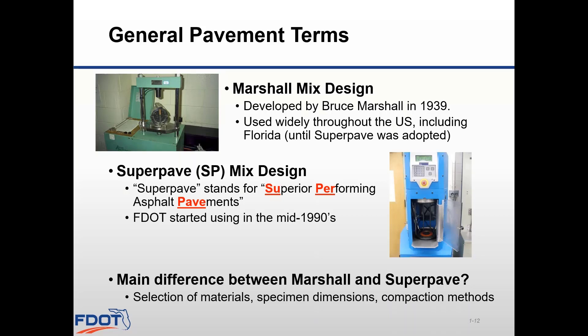The main difference between the Marshall method and SuperPave is that SuperPave uses performance-based criteria for asphalt mix design, considering the material properties of the asphalt and the aggregate, so there is a direct correlation to performance in the field. Adopting SuperPave caused us to improve our specifications. As a result of the SuperPave gyratory compactor, which could simulate loads associated with higher traffic volumes, as well as SuperPave aggregate consensus properties, mixes in Florida were significantly stronger and much less likely to rut.